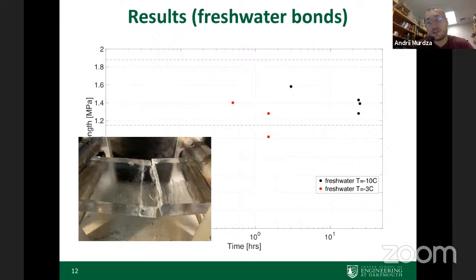And the reason for this is that when we create this bond, we spray with a fine mist, and probably the grain size is very, very small within the bond. And as we know, the smaller the grain size, the greater the strength of the material. So that's a possible reason.